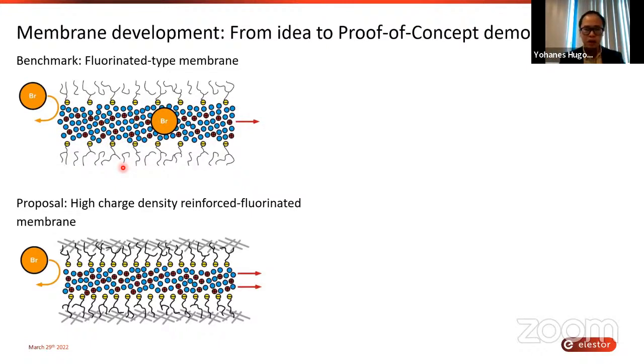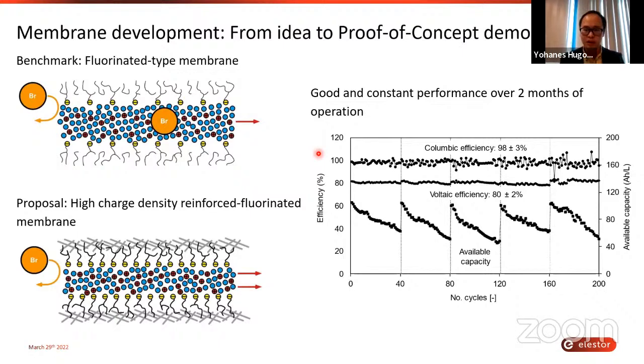From this idea, we figured out that we can realize it and move to the proof of concept with the electrospinning technique. Again, I need to thank Miss Begüm for explaining very nicely how to produce this type of electrospun membrane, where we electrospin a mat and then process it with a hot pressing process into a dense membrane. I did this a few years back, and I already tested it in a coin cell that showed really good performance, very stable over a 2 month period of operation. And now Elestor and Innovenso will try to commercialize this idea.